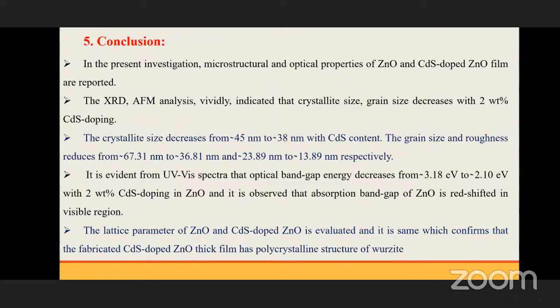Conclusion. In the present investigation, the microstructural and optical properties of ZnO and ZnO CdS doped thin film are reported. XRD, AFM analysis, and UV visible indicated the crystallite and grain size and band gap energy. The crystallite size decreased from 45 nanometer to 38 nanometer with CdS content. The grain size and roughness reduced from 67.31 to 36.81 nanometer, and roughness from 23.89 to 13.89 nanometer respectively. It is evident from the UV visible spectra that the optical band gap energy decreases from 3.18 electron volt to 2.1 electron volt with 2% CdS doping in ZnO.